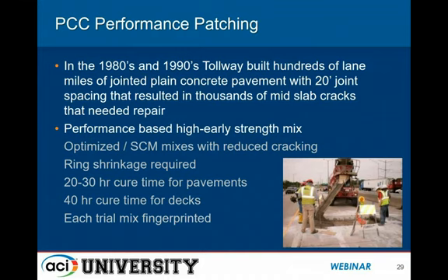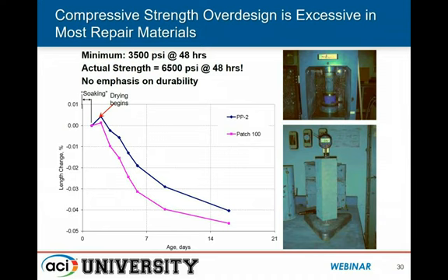And some of you may be thinking that, well, doesn't that add a little bit of additional risk in terms of making our strength? And yes, I agree with that. There's some additional things that you need to watch for during the trial batching process. You especially need to make sure that you have your admixture dosages dialed in, and then as the temperatures outside begin to change, that you have that relationship between the early strength and your accelerator dosage figured out so that you're not relying purely on the cement to get your early strength, because I think that's where folks run into trouble with cracking.